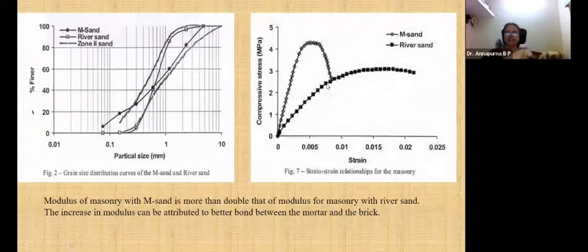And here is the compressive stress, this is the stress versus strain graph. So this is for M sand and this is for river sand. So here the M sand has lesser strain and high strength, and the strength is similar to a high strength concrete. The modulus of elasticity of masonry with M sand is more than double that of masonry with river sand. So the increase in modulus can be attributed to better bond between the mortar and the brick.